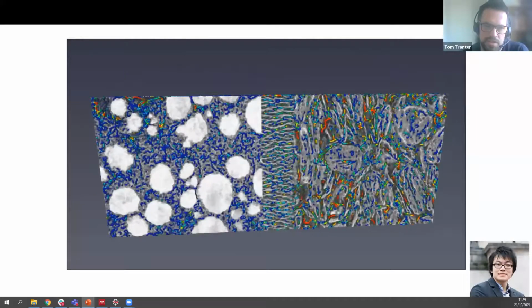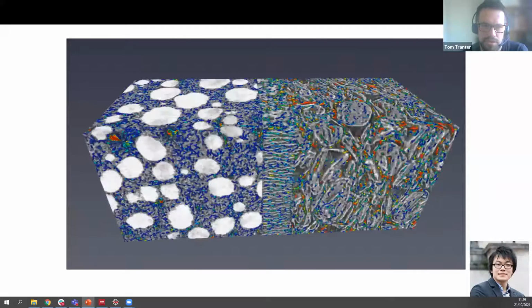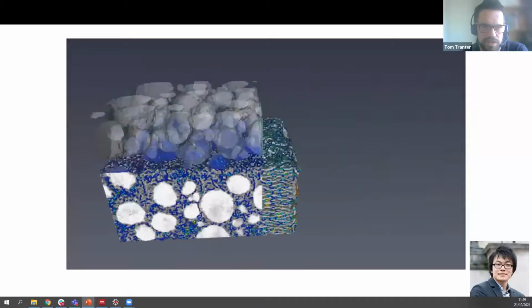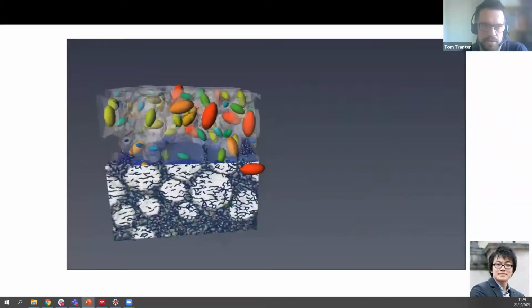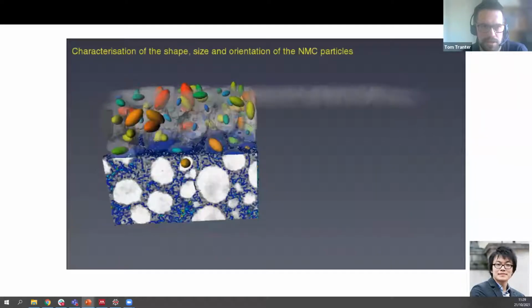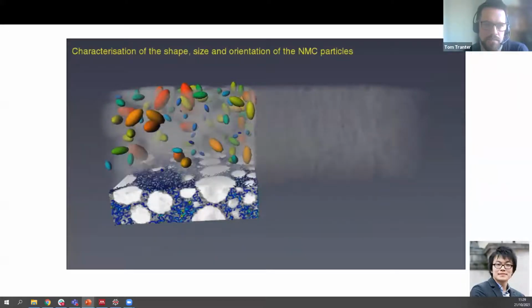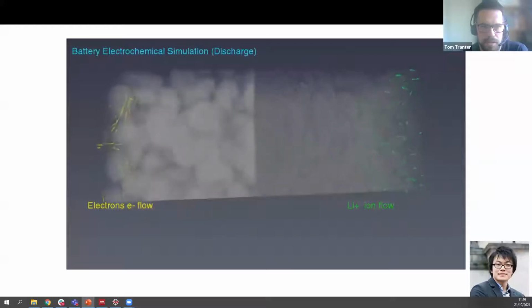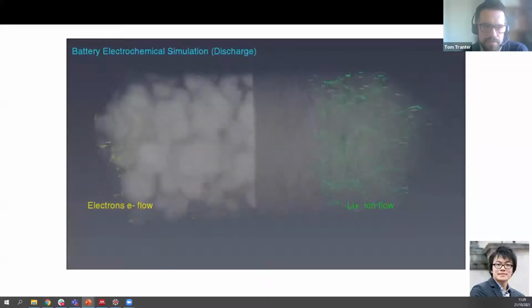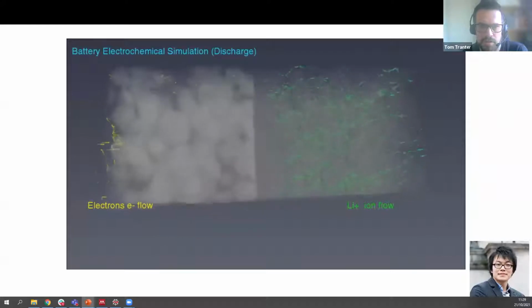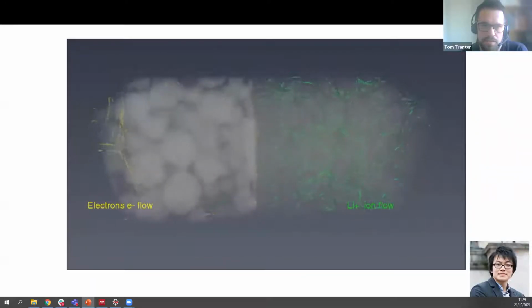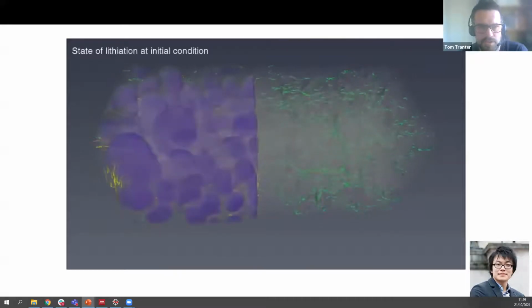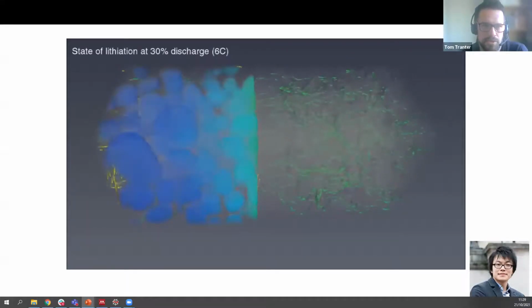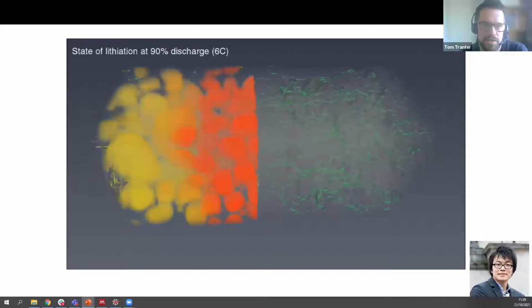And you can get statistics on the porosity, pore size distribution, tortuosity, and then on the active material side, you can look at things like shape factors, and again, particle size distributions. And then we can simulate electron flow through the solid and lithium ion flow through the electrolyte, and participating reactions at the interfaces, at the particle surfaces. And we can resolve the state of lithiation at various states of charge.